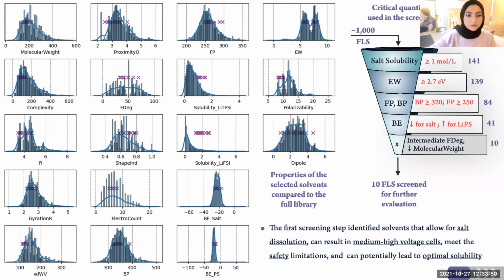And this plot here shows a distribution of the properties of these solvents in purple scatter points, compared to the properties of the overall library. Therefore, this step allowed us to identify solvents that allow for salt dissolution in the electrolyte, can result in medium to high voltage cells, meet the safety limitations, and can potentially lead to optimal solubility of the lithium polysulfide species.